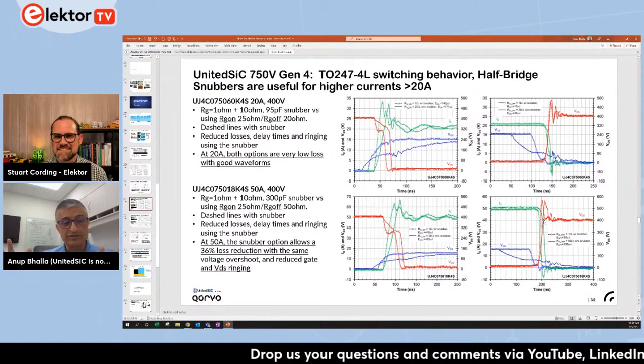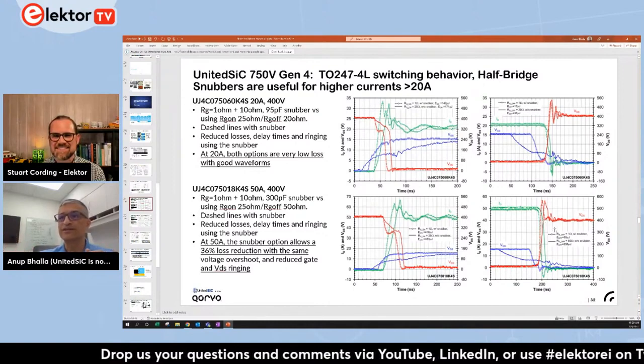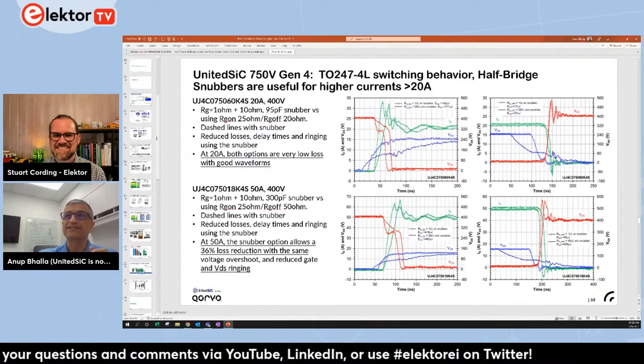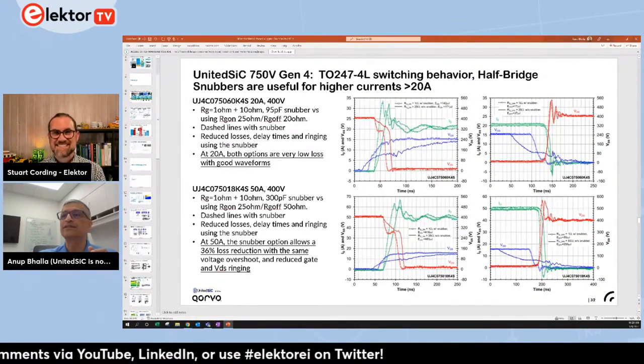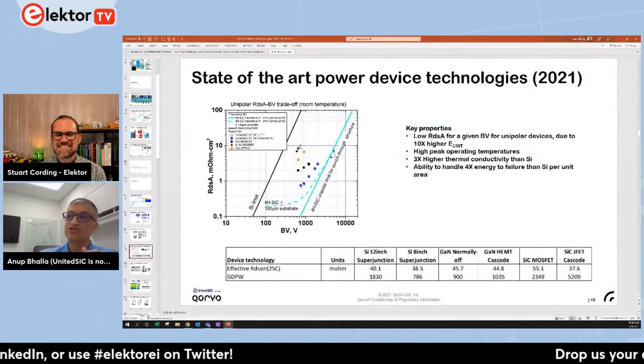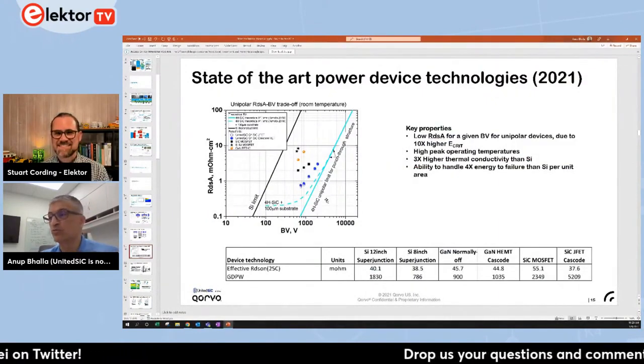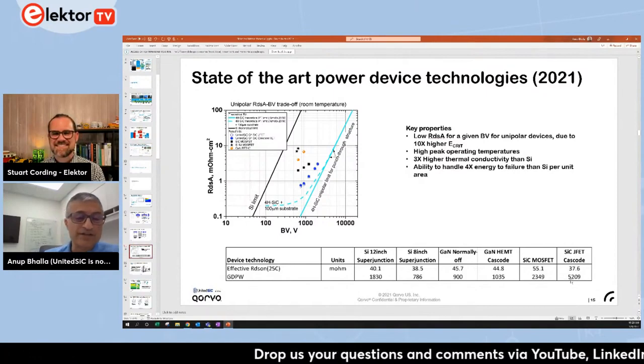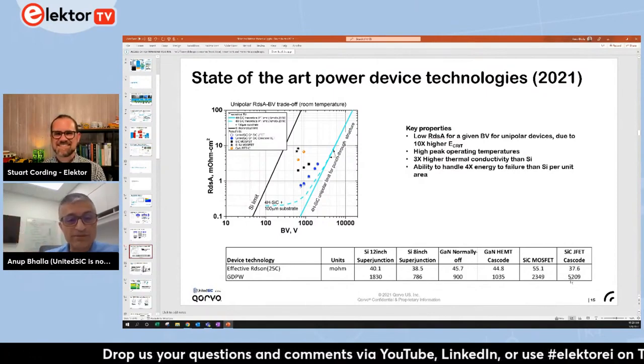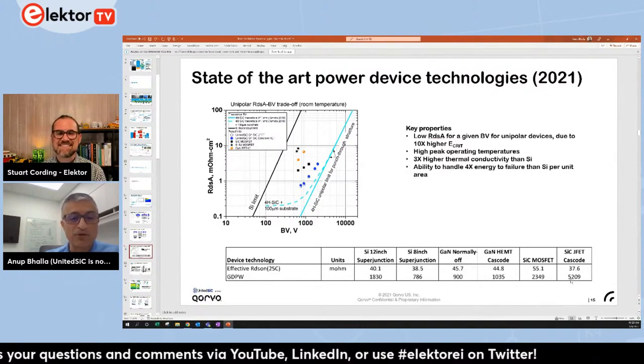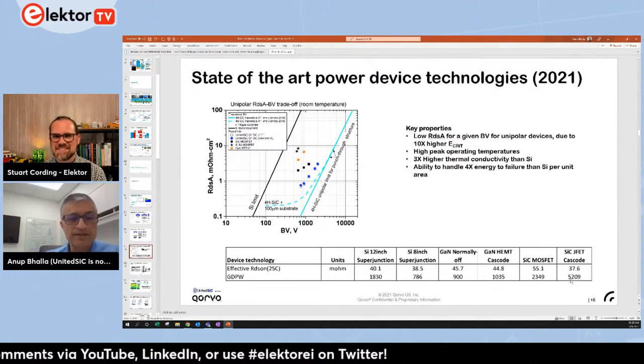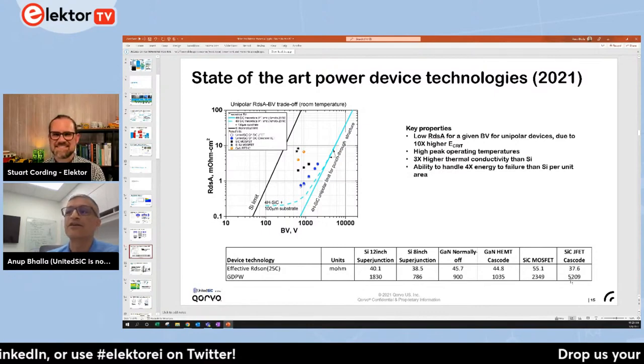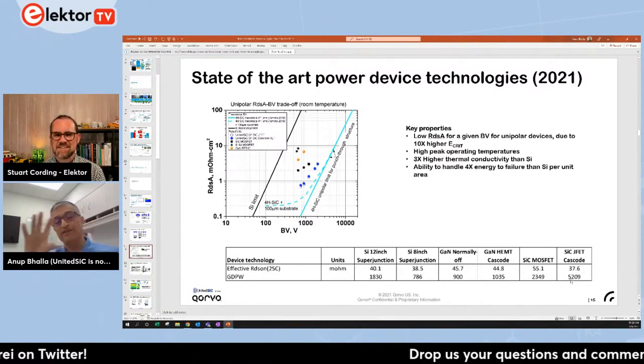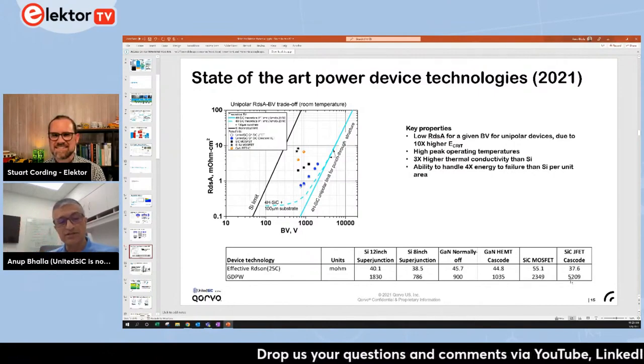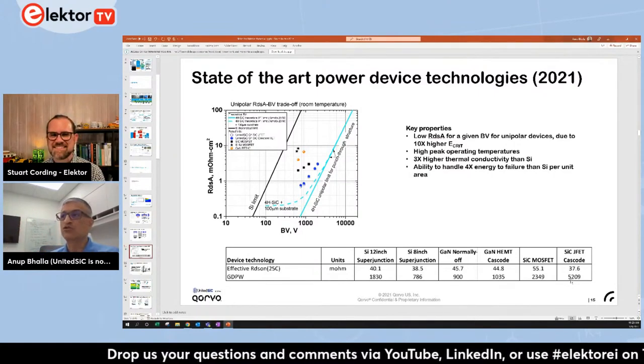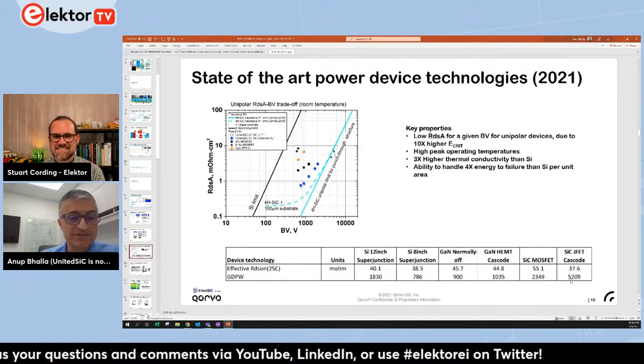At the end of it, though, like I showed you in a picture, the resistance that we get out of a centimeter square of chip size is so much lower than silicon devices that we get so many more die per wafer if you're trying to target a certain resistance, that I think at this point we are able to be fairly competitive with superjunction type MOSFETs, despite the higher cost of building silicon carbide. But the factories, the fundamental steps are rather similar. Factories that do the actual processing of the wafers look pretty much the same.